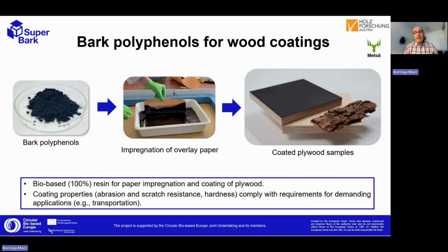And for this type of coatings, for the plywood coatings, this is called paper impregnation, and so it's an overlay paper which is pressed onto the actual wood product. So you have a paper, you impregnate it in this bark-based resin, and then you put it on the plywood, you press it, and you have this brownish coating. And this actually performs very well.